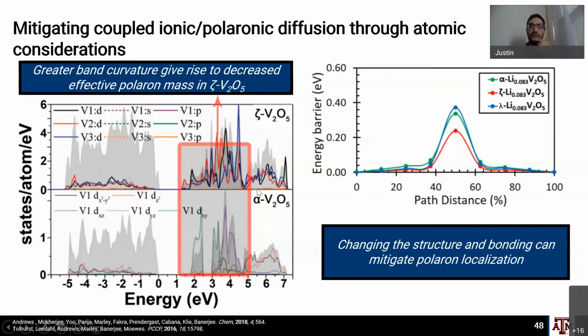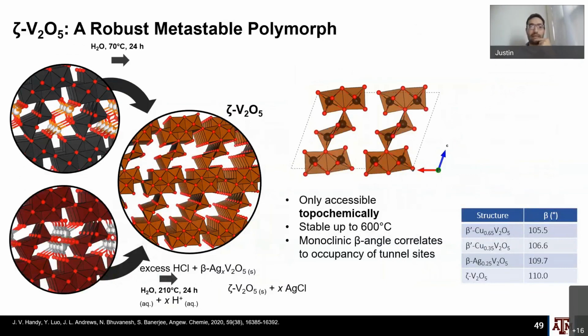And so the vanadium split-off d_xy state that you see here in alpha V2O5 is not present in zeta V2O5. By having a larger number of vanadium states that are accessible, it essentially reflects the increased covalency of the structure. And so that was one thing that we were excited to look at.